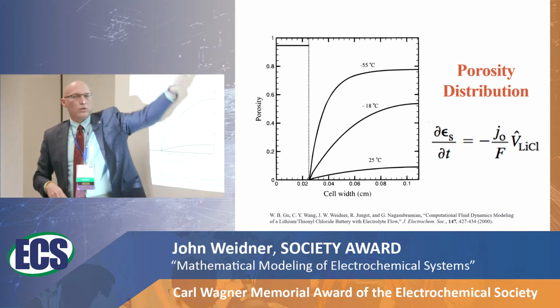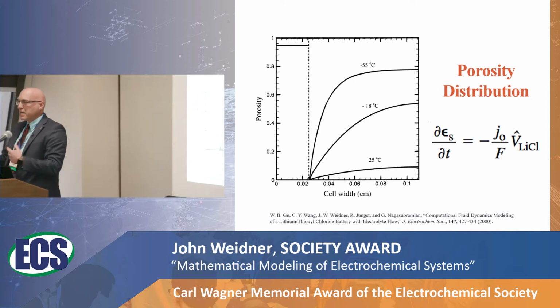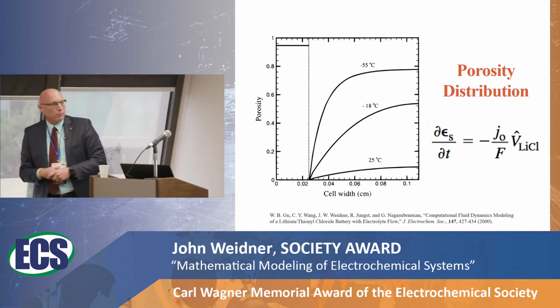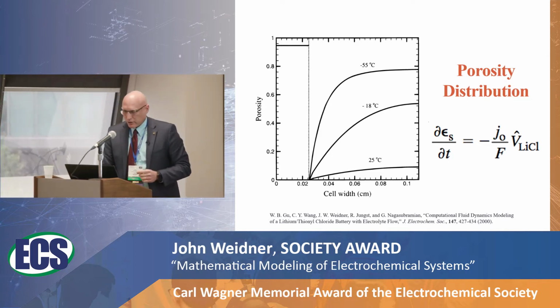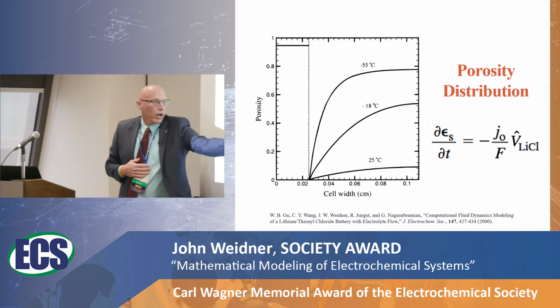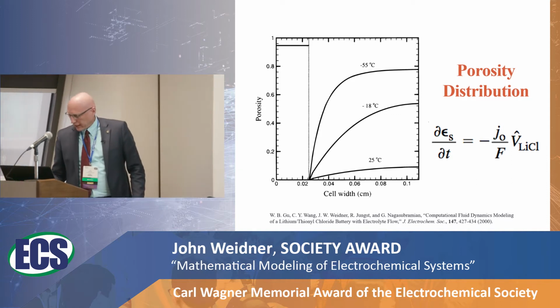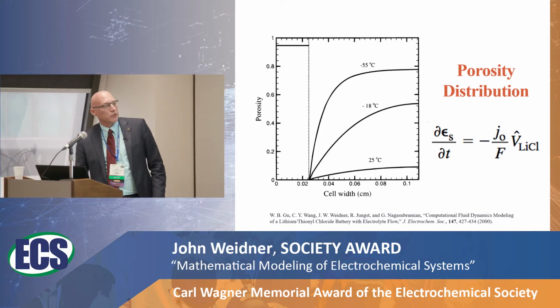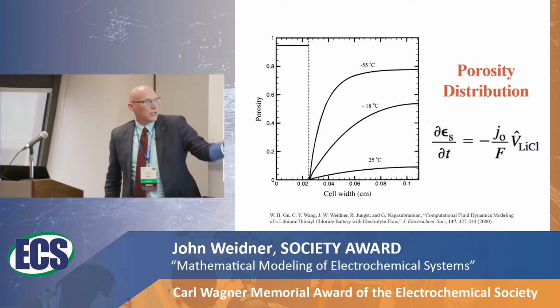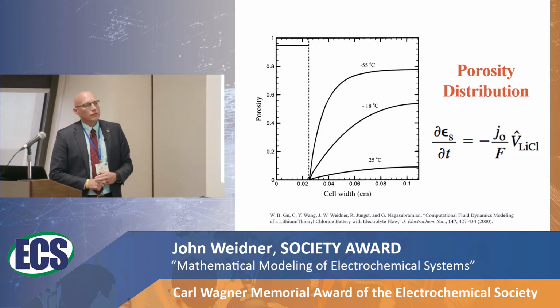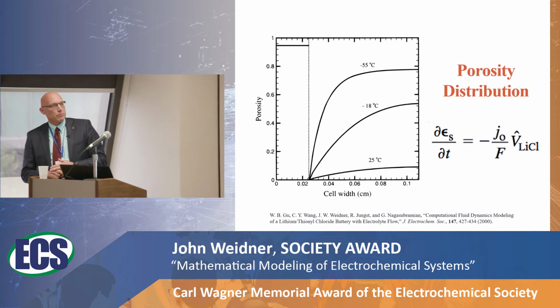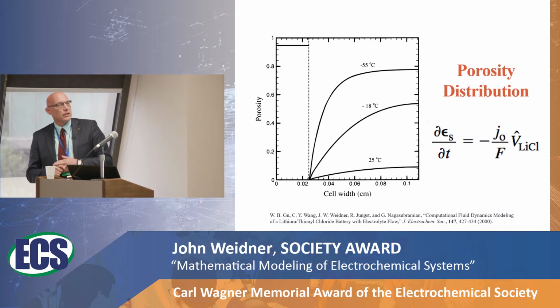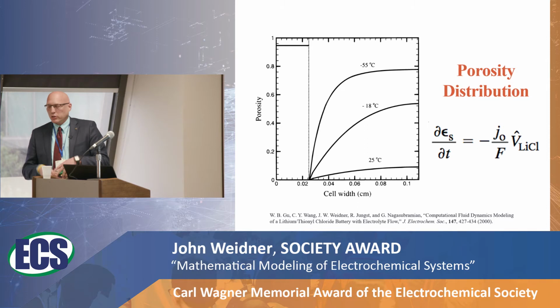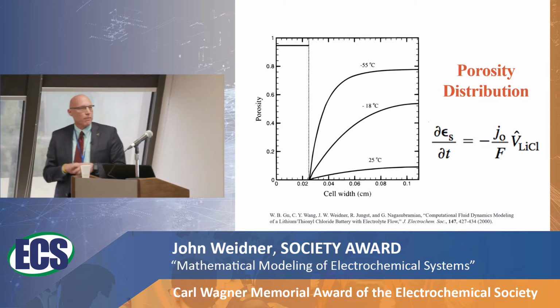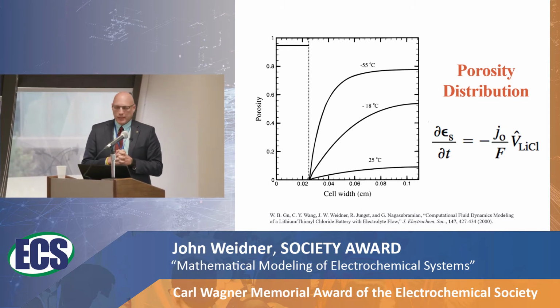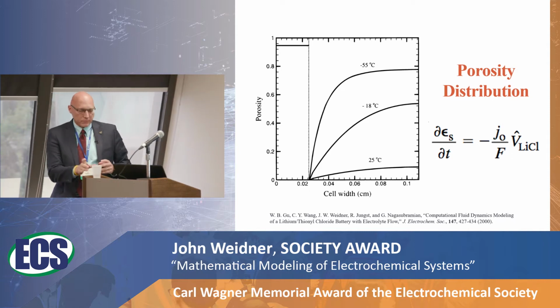Although in the back of the electrode, there's still a very high porosity, meaning there's still a lot more reaction that could have occurred, and hence why the capacity drops off dramatically as you decrease the temperature. So at these very low temperatures, you had a lot more capacity left that you weren't able to access. At room temperature, you almost access the whole amount. So again, there's some insights that you can get that experimentally you would have a hard time measuring.